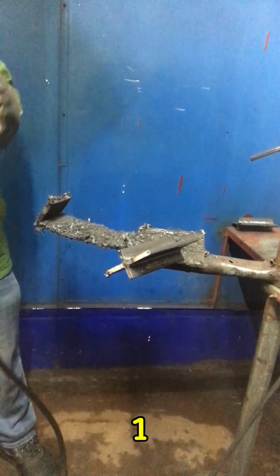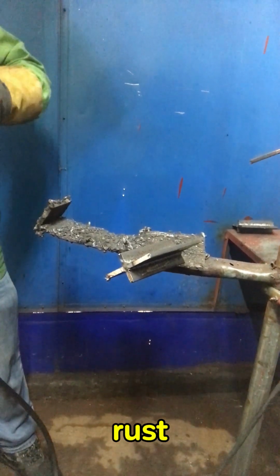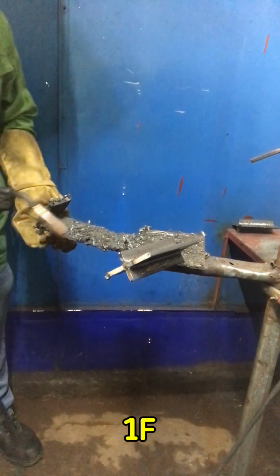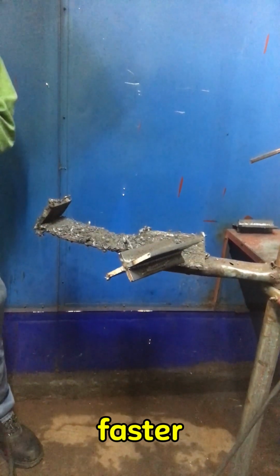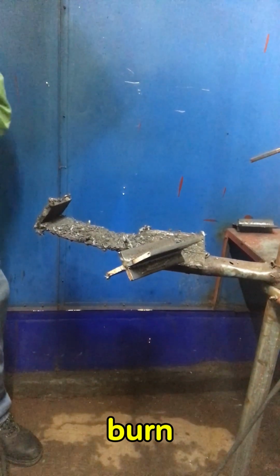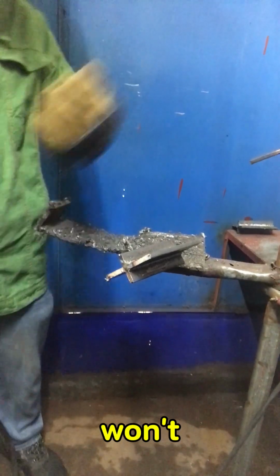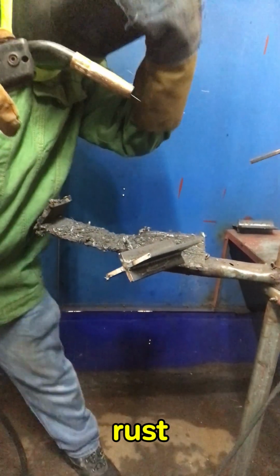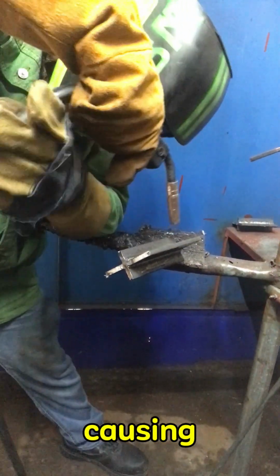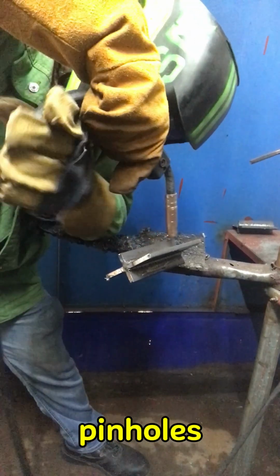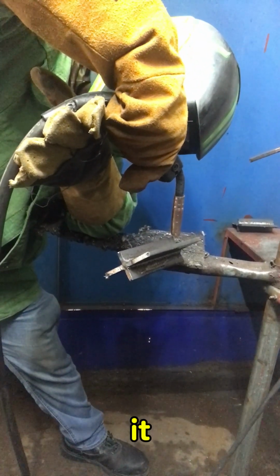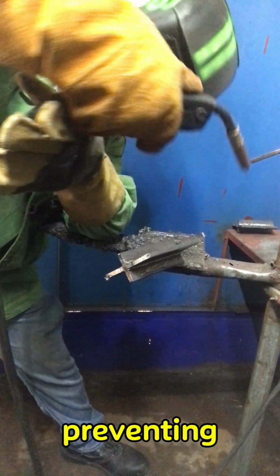Now, let's get into the mistakes. Mistake number 1. Welding over mill scale, rust, or oil. Because 1F allows you to run hotter and faster, beginners think the arc will just burn off the mill scale. It won't. Heavy mill scale and rust trap gas in your weld pool, causing porosity, those ugly little pinholes that destroy strength. It also acts as an insulator, preventing full penetration into the root.